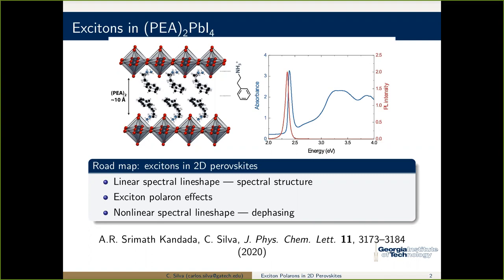And so if we take gallium arsenide and we work out what the permittivity function is as a function of frequency, we see that between the static and the high frequency limit, there's a variation of a factor of a few. But if we take the bulk lead iodide perovskite, and look at the permittivity function between the static and the high frequency limit, it's about a factor of 100 difference. Okay, this really tells you that this is a very dynamic system.